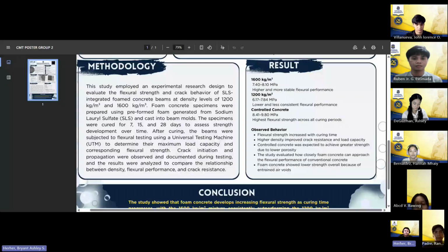By analyzing these results, flexural strength of the concrete beams increased with curing time, higher density has better crack resistance, so reducing void content can increase load capacity. Controlled concrete achieved greater strength as its internal structure is more dense compared to foam concrete that has entrained air voids formed due to the incorporation of a foaming agent. The study evaluated how closely foam concrete can approach the flexural performance of conventional concrete. Our next reporter will be Ms. Bowie.